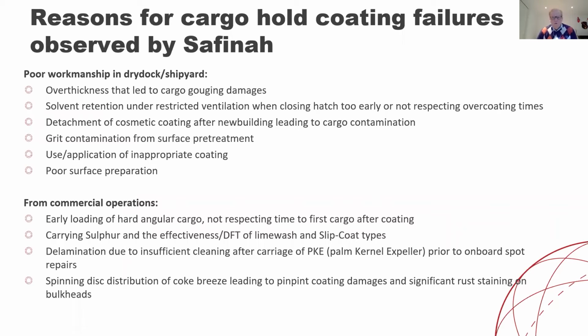If I try to sum up or class the different failures that we have observed in the various cases we've been looking at, doing inspections, failure investigations and failure analysis, we will class them into two. One is poor workmanship in dry dock or shipyard, and the other is failures from commercial operations. The typical failure we see with regards to workmanship is over thickness that leads to cargo gouging damages, and we do